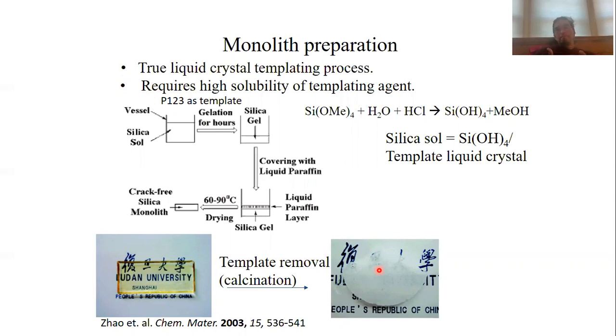framework. You do not have fully polycondensed the framework typically before you remove the template, so there are also always silanol groups left, and these silanol groups can then further condense upon calcination to form silicon oxygen silicon groups.